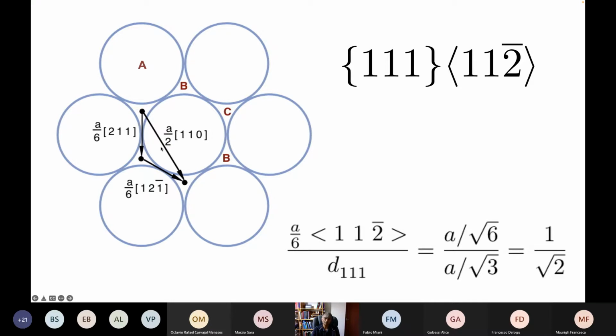However, this direction a/2 [110], where a is our lattice parameter, can be split into two 112 type vectors here, a/6 [211] and a/6 [12-bar-1]. And if I translate the layer above this layer from this position, which is a C position, to a B position, then I actually change the crystal structure. I've introduced effectively a fault in the lattice. And if I carry out this translation on every single 111 plane, then the result is a twin, a mechanical twin in the austenite. So the displacement is a/6 [211] here.